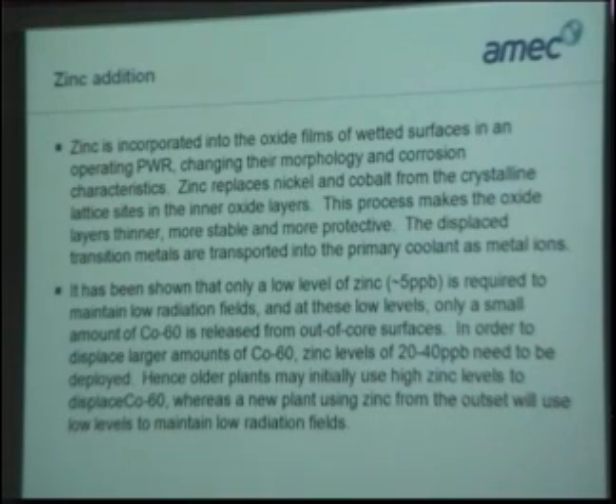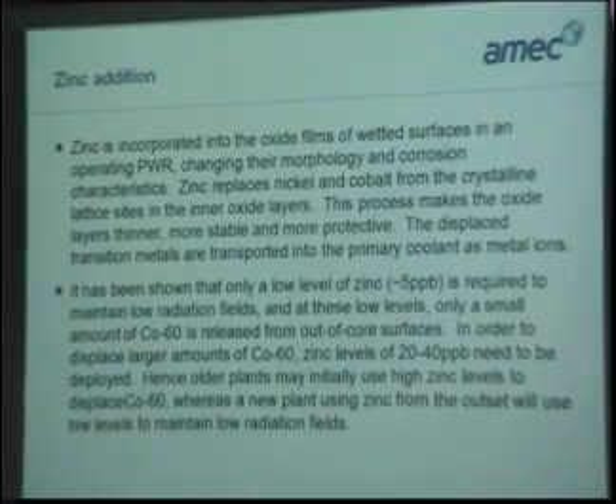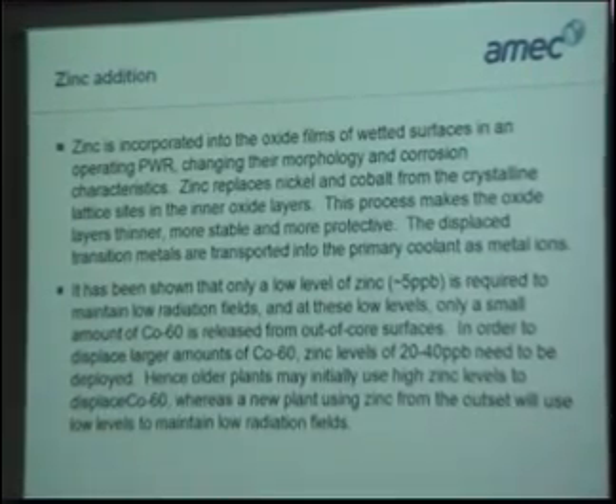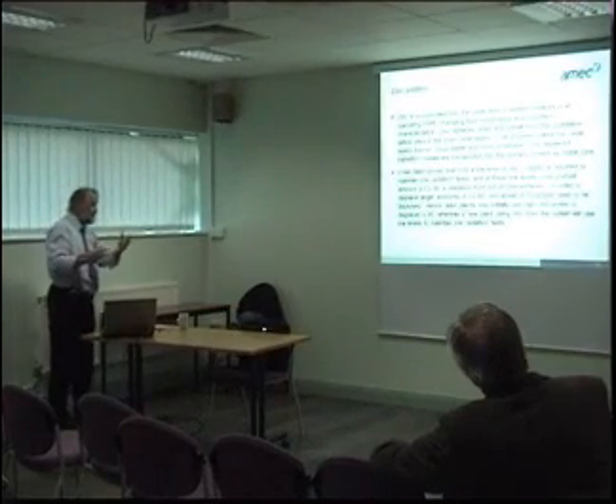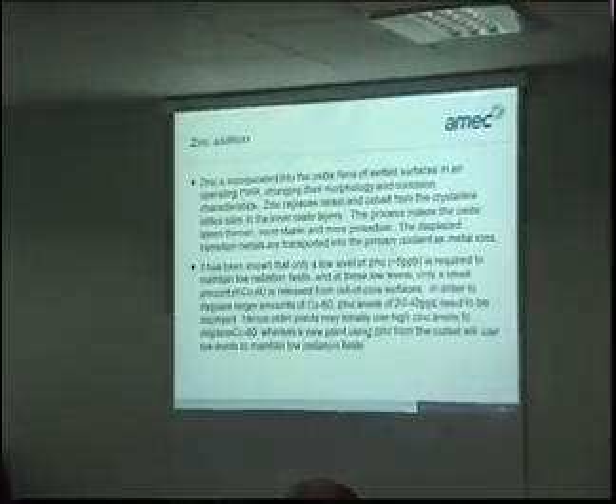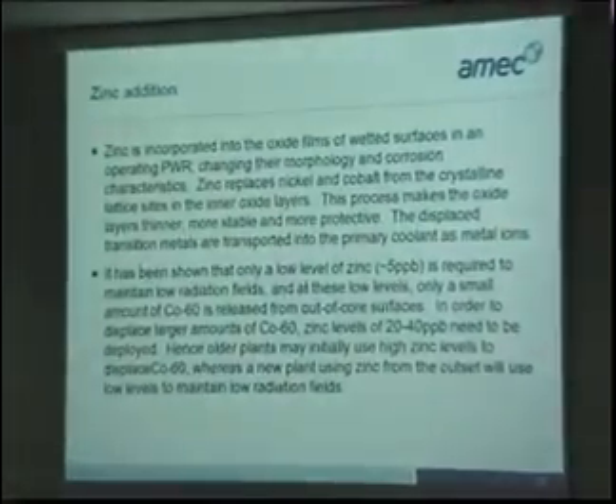I've mentioned zinc addition. Zinc's a D-block metal, and it can replace nickel and cobalt in the oxides on surfaces, which means, of course, that it minimises their release later on, or actually minimises their absorption and formation. And so there's been a big debate about zinc addition in pressurised water reactors, and quite a lot of plants have adopted this with success, both old plants and new plants.